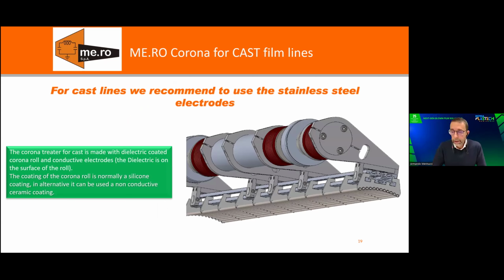Regarding the electrodes, as I told you before, they are completely different from the segmented electrodes we use in blown film lines, and these are the same electrodes we use for the big 10-meter lines. They are stainless steel electrodes, specifically designed to allow a free expansion of all the elements in a way that you do not lose the gap, which is a very important characteristic on a corona treater, especially if you have to guarantee a gap of 2 millimeters on a 5, 6, 7, 10-meter line.